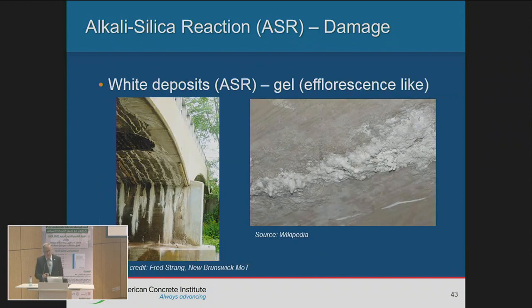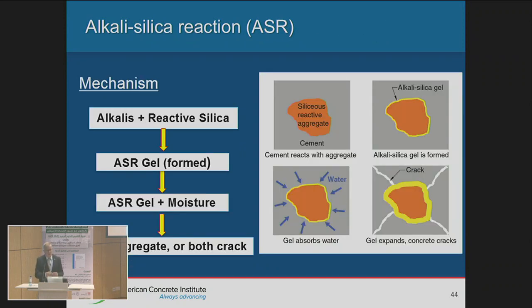And the way you find out that you have this ASR is that there are gel deposits around the cracks, what we call the efflorescence-like gel. The way that occurs is when you have alkalis, they react with the silica, okay? They create around the aggregate what we call the alkali silica gel. If there is moisture or water within the mix or that comes from the outside, that gel expands. When it expands, it takes volume, and that volume needs space. So it pushes against the concrete and you get those cracks.